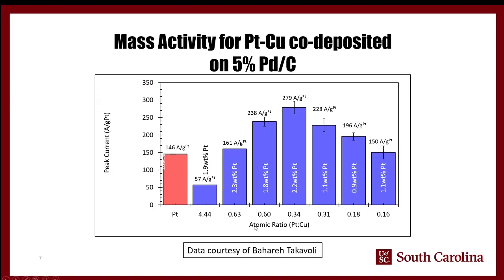So here's some older data as well from Bahari Takavoli. This was with platinum and copper, and what she actually found was that having a majority of copper compared to the platinum was where the peak activity occurred. So over here on the left, this is pure platinum. This is 20 weight percent platinum on carbon. It's about 146 amps per gram of platinum.